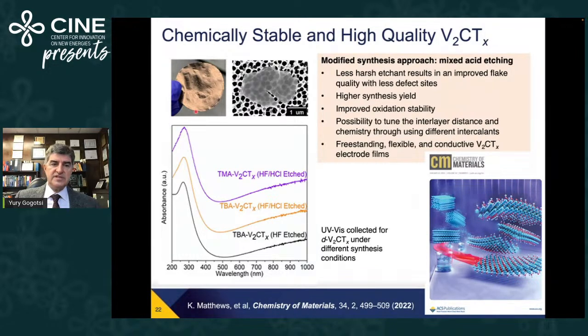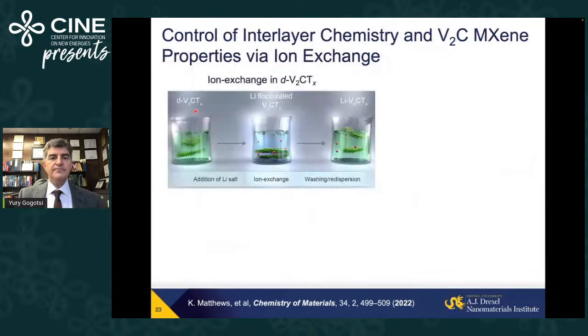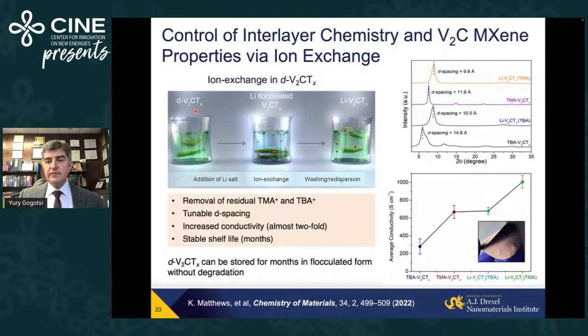And when we make flakes, you see this one will be golden foil if you make it here, just by exchanging, for example, the initially used tertiary amine with lithium, we get very high environmental stability and also increased conductivity for this material. So the message I would like to leave you with here: a huge number of structures and compositions, a very wide variety of properties, can be produced in quantity by a highly scalable method, can be processed into films, porous networks, aerogels, and introduced into metal and ceramic matrix composites by processing from aqueous solutions.